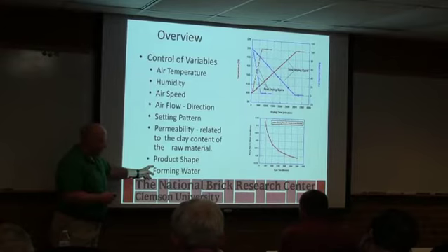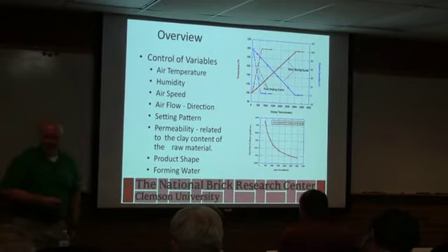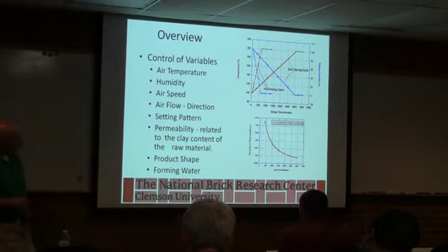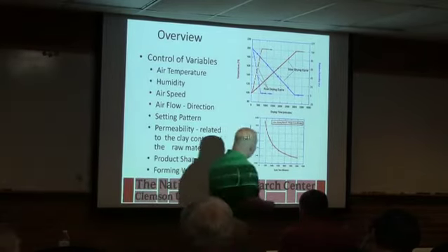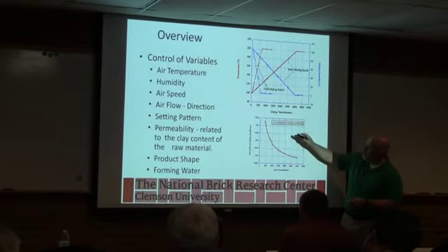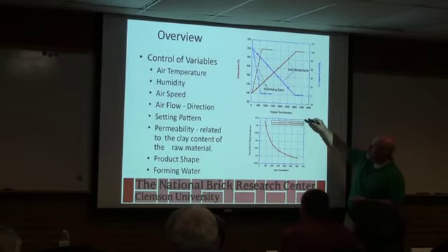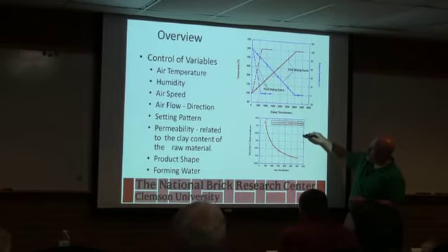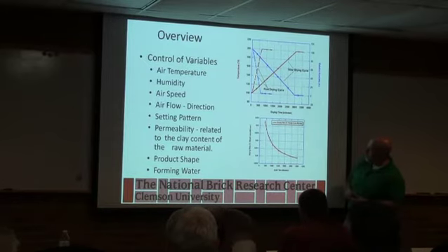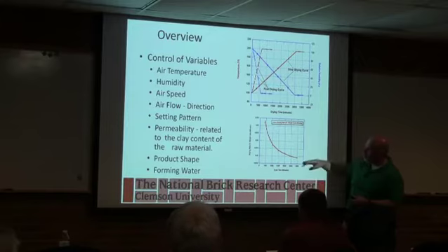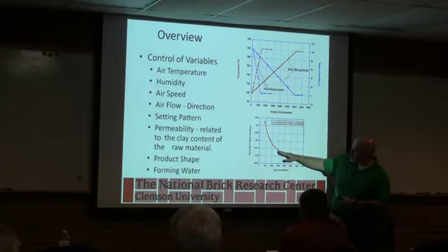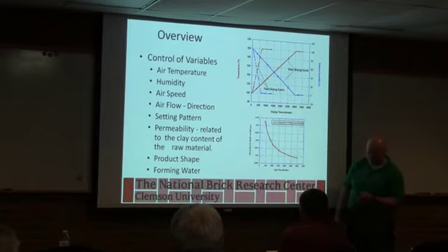So this is a balancing act. You can't have too little water or you're going to have extrusion problems. But with too much water, the brick will be soft and it's harder to dry. So it's always something to consider. But what we were trying to do is figure out how fast we could dry. So we played with basically the temperature, humidity, and airspeed, trying to get different drying rates to see where we saw cracks develop in the brick and to figure out how fast we could dry. So basically, what we're doing here is increasing the drying speed by manipulating those things.